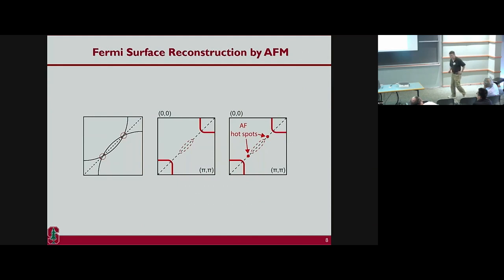So the takeaway of this will be, if you have a reconstructed Fermi surface due to a much higher energy scale spin density wave, then you will open up a superconducting gap on top of this reconstructed Fermi surface.